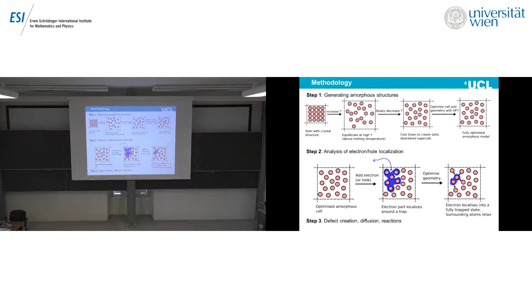So this is the methodology which we use. We need to produce an amorphous structure first. So what we do is we start from a crystal and use a melt-and-quench procedure, in most cases with an interatomic potential. So we use some force field, use some molecular dynamics, melt our sample, and then slowly decrease the temperature and quench it. Slowly, in this case, is quite fast by experimental measure. We go down at about 1 Kelvin per picosecond. Experiments barely can reach that, so we are much slower.